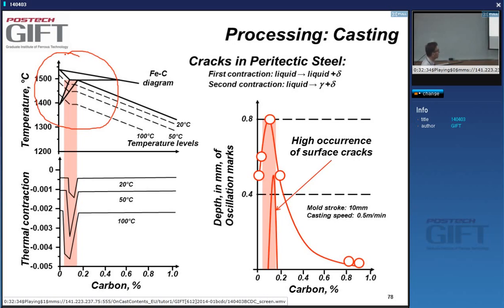There are two contraction steps during solidification. The reactions are shown here: when the liquid solidifies in this zone, it first goes to liquid plus delta, so there is a contraction during solidification. And then there is a second contraction when you go through the peritectic reaction, where the liquid becomes a mixture of gamma plus delta.